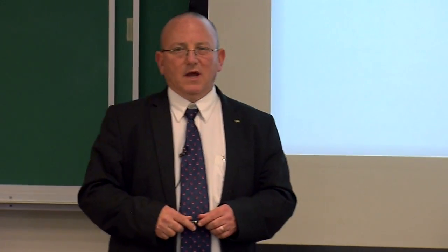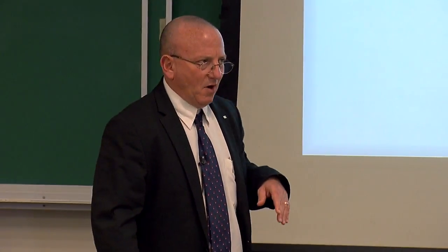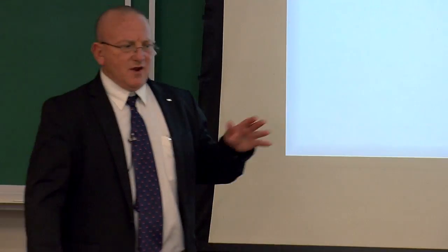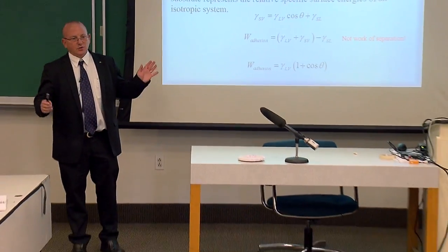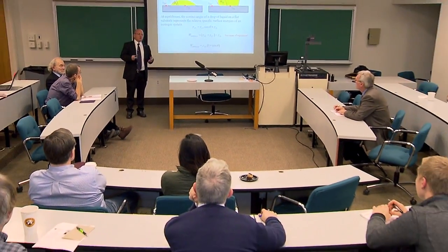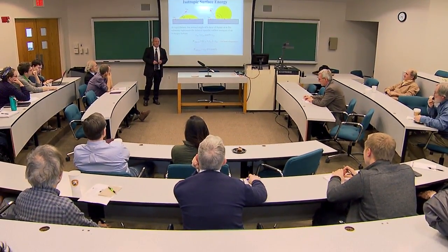And that's why we actually need to do this in the SEM or the TEM, because in order to be in length time scales that are of some possibility in experiments, then these are pretty small particles. I think for nickel of a particle of about 150 to 200 nanometers, something like 6 hours with the surface diffusivity at 1,200 degrees, assuming that there's at least one screw dislocation around in the area, should easily be accessible. So what we do is we calculate that and then we just double it and wait a little bit longer.